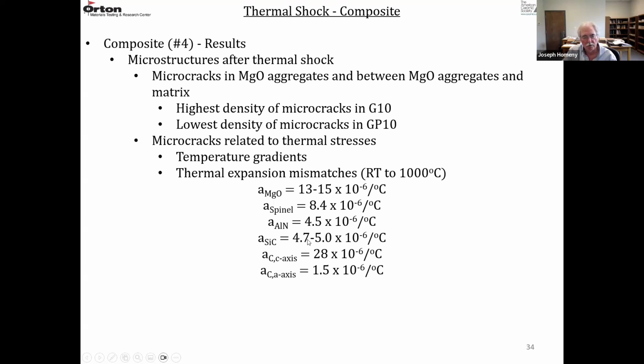So there's thermal expansion mismatches. The MgO is the major phase, and so is the carbon. So carbon is in the form of flake graphite, which is anisotropic. So in the C-axis, where there's weak bonding, it's 28 times 10 to the minus 6. And in the A-axis, where there's strong covalent bonding, it's really low, 1.5 times 10 to the minus 6. So if you look at these thermal expansions, especially for MgO and graphite, you can see the mismatch leading to a lot of microcracking in the matrix.